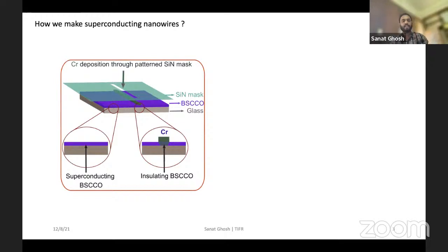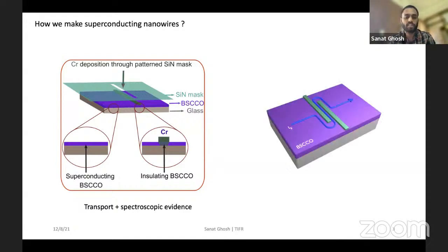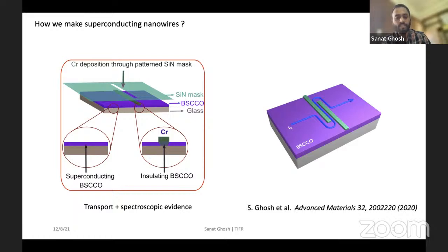The main idea behind it is that the system that we use is the superconductor BSCCO, which is a high TC superconductor, and this is a van der Waals material and can be exfoliated like graphene. This cartoon shows the main message: when we deposit chromium on the surface of a thin layer of BSCCO, chromium makes the underneath BSCCO insulating. We have done transport and spectroscopy studies to show this behavior. If we use this technique, one can define the nanowire by simply depositing two chromium lines with a gap in between them, and this gap defines the nanowire geometry. I will not go too much into the details of the process. The details are shown in this manuscript.